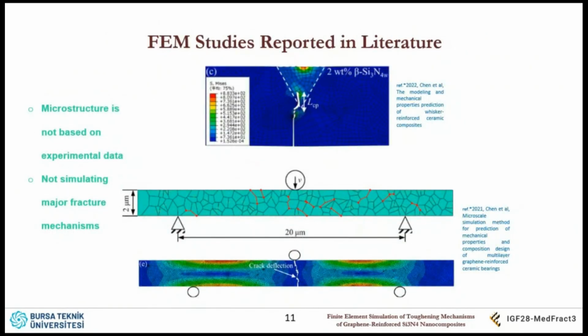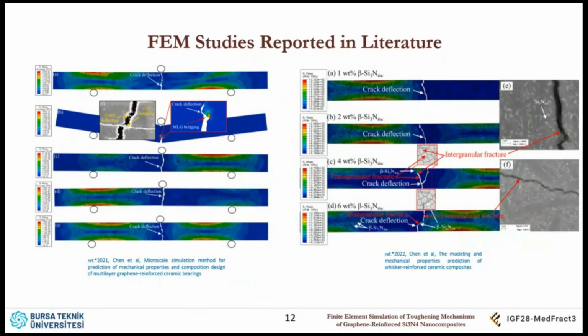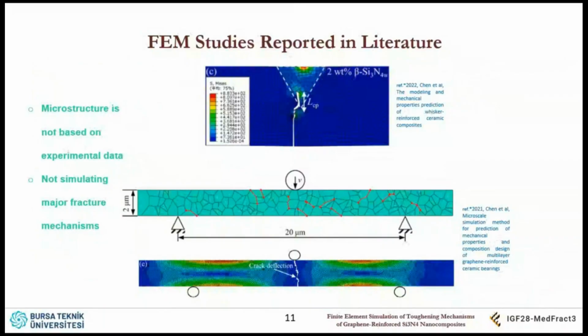So what about the studies done previously for the simulation of the toughness or deformation mechanisms of these materials? There are few studies, 2 or 3, made for this purpose. By Chen et al., and the same group, I think. They are presenting some useful information. It's good. However, the crack path they could obtain could just provide 2 mechanisms. One is crack deflection, and the other is crack bridging. So there is really a small number of toughening mechanisms provided by their studies. And their studies do not incorporate microstructure based on the experimental findings. And also, as I said, they are not simulating major fracture mechanisms.